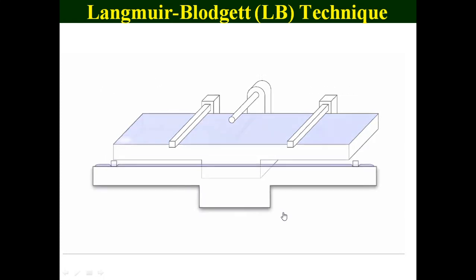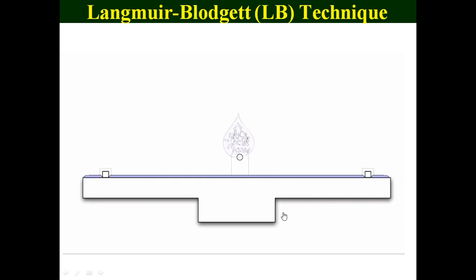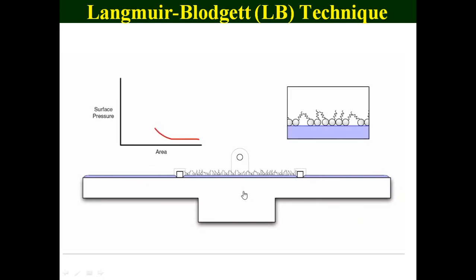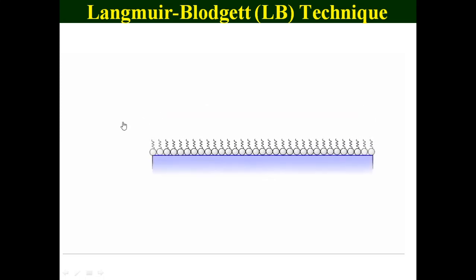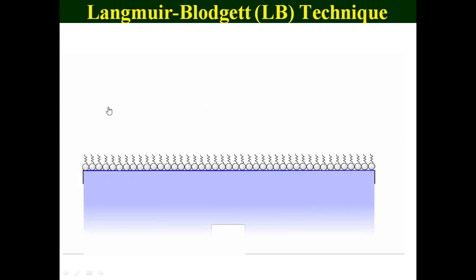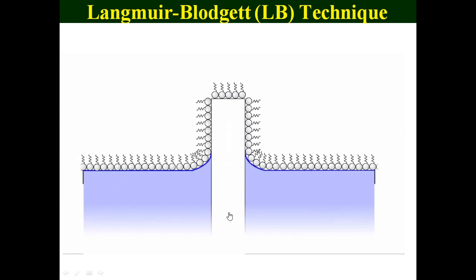And this is a Langmuir trough, and when some drops of dilute solution of suitable molecules are sprayed, the solvents evaporate and the molecules lie haphazardly on the water surface, and then the barrier is compressed slowly. With the compression of the barrier, molecules come closer and closer, and this isotherm curve shows the surface pressure increases. And when the surface pressure attains almost the steep region, we get a crystalline arrangement of the molecules on the two-dimensional surface. And then the solid substrate can be taken out from within the water surface, so that a monolayer is deposited on the solid substrate.